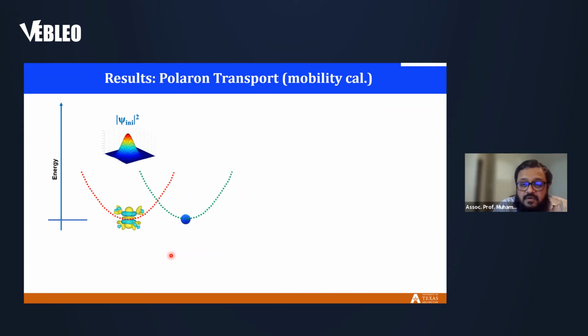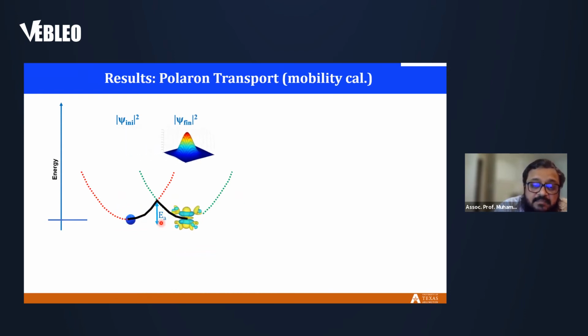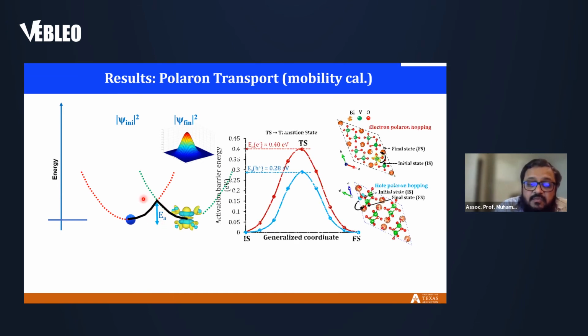Now, a quick view of how polaron transport happens. It's basically hopping state to state. So if this is an electron polaron, it will hop from one vanadium site to another vanadium site. If it happens, it has to go through this energy barrier. We call it the activation barrier. We calculated the activation barrier for both electron and hole. The hole activation barrier, about 0.3 electron volt, is lower than the electron activation barrier, which is about 0.4 electron volt. So from these numbers, we can see that holes can move with a higher probability than electrons.